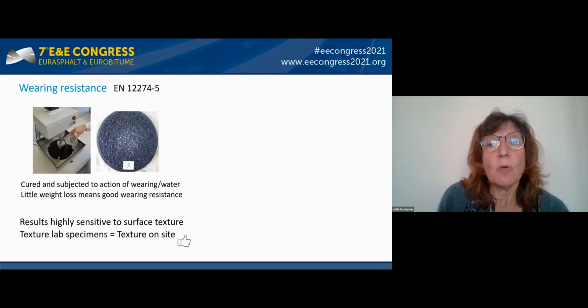Wearing resistance is then measured on specimens the size of a pizza, which are cured and conditioned in water before testing. And then the surface is subjected to wearing by the action of a rubber hose while being submerged in water. In this test, the surface texture has a significant impact since the rubber hose has less grip on a smooth surface, and therefore it's crucial to produce specimens with equal texture, representative of the texture on the road. This has been verified by texture measurements made on job sites with the same mix compositions.